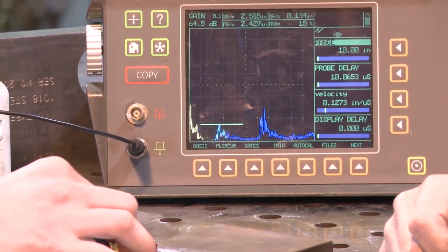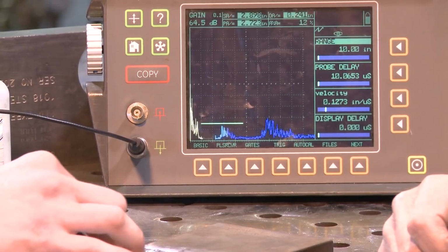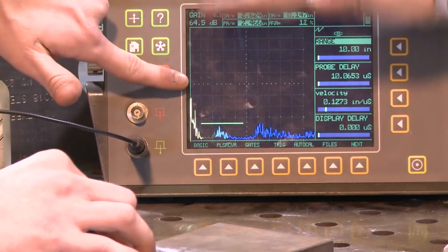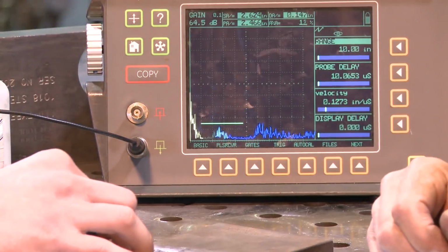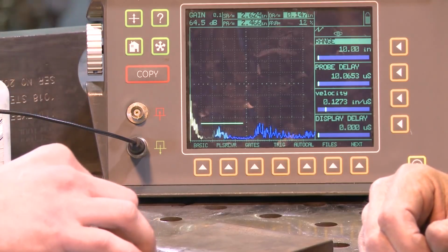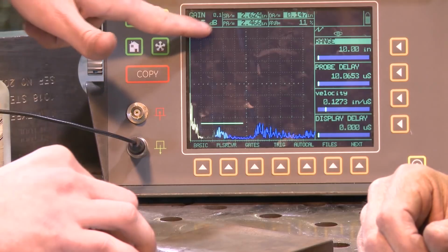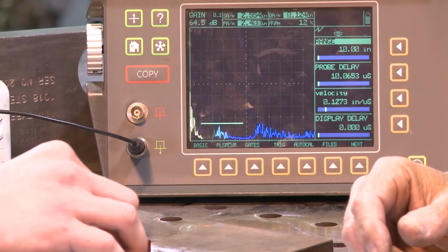And if that weld signal stays there throughout this whole scan, my life is good. However, if it breaks this plane, this 50% screen height here. Here? Yeah. This screen height? Here. Yep. That's what I calibrated that 60 thousandths hole to, to tell me that anything that comes up to here, 100%, is 60 thousandths. So if it comes up halfway, it's half of 60 thousandths. Right? So anything that size, we definitely want to interrogate.